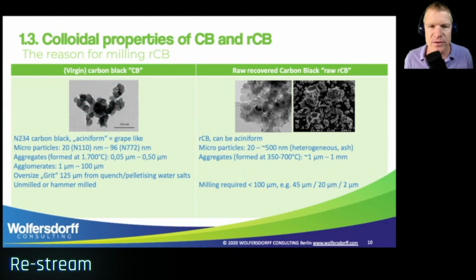They are clustered into aggregates, and these aggregates are fused together at about 1700 degrees. This is the smallest version of the carbon black we can have in any kind of system. The size is 0.05 micron to 0.5 micron. So very small, and the aggregate size distribution is very important for the performance in tinting and coloring. Now there are agglomerates. They could be several aggregates clustering together with van der Waals forces. They could have any size between 1 micron and 100 micron.